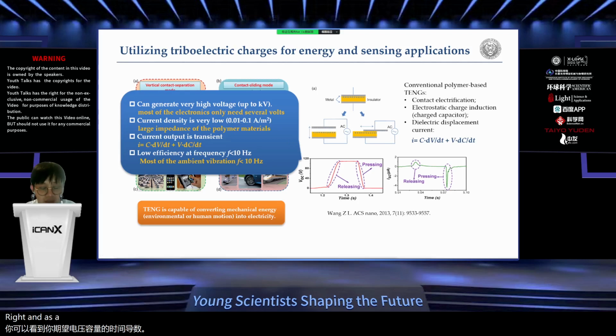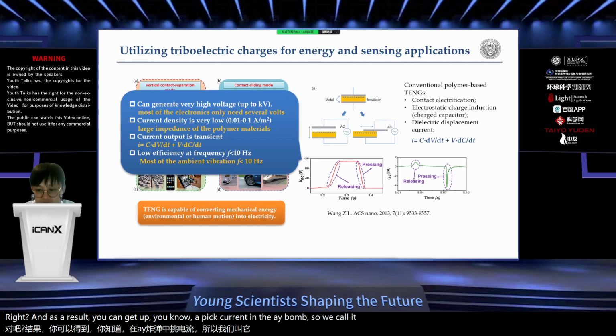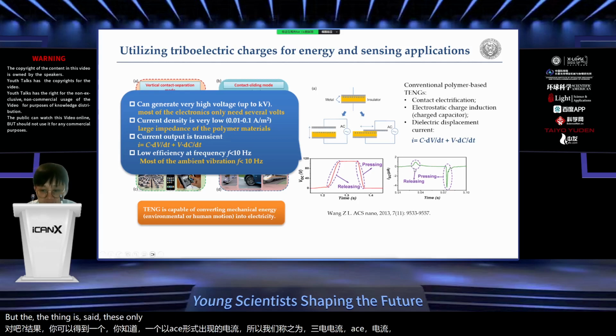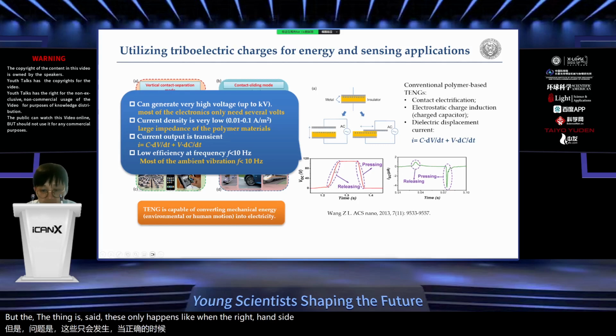And as a result, you can get peak currents in the AC form. So we call it triboelectric AC currents, right? But the thing is that this only happens, like on the right-hand side, when you have a changing voltage, right? And then the form of these currents is actually transient pulsed currents, right? And that means if you really integrate the product of voltage and current, which is going to be the power, there will be many times in this time domain which cannot give you power outputs.